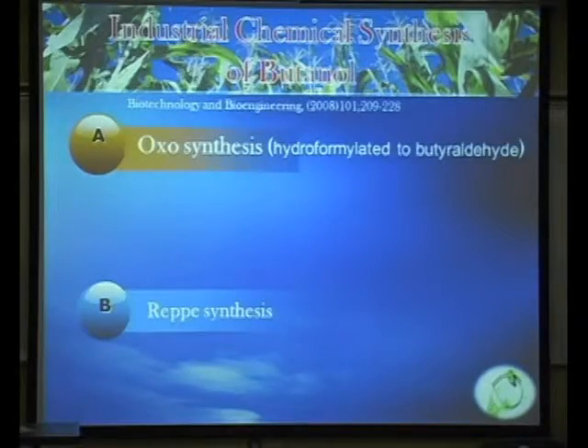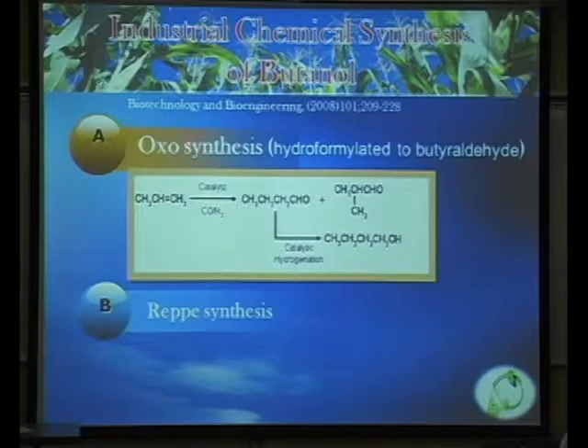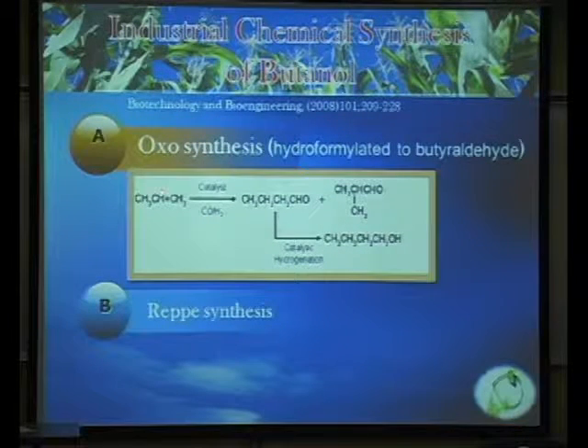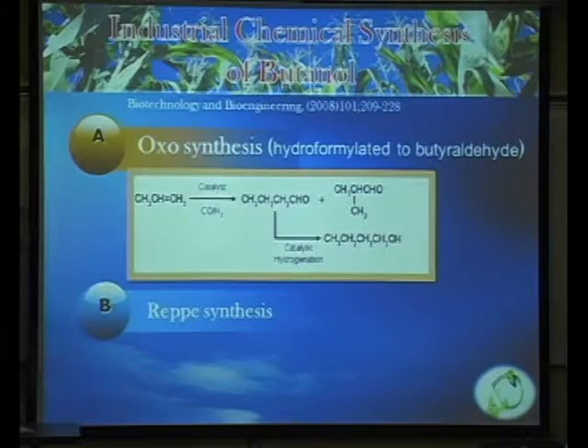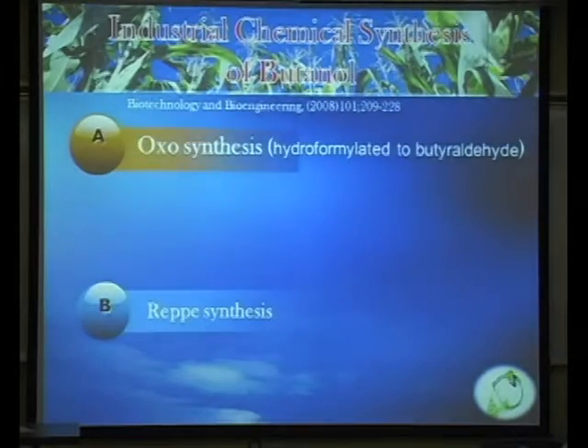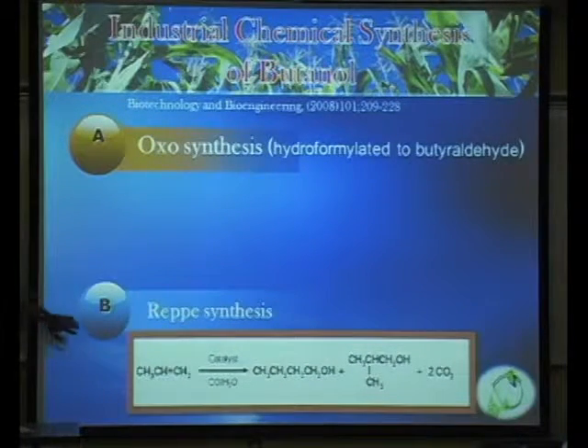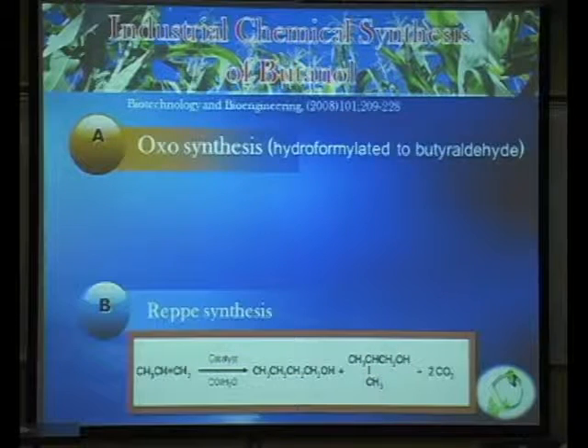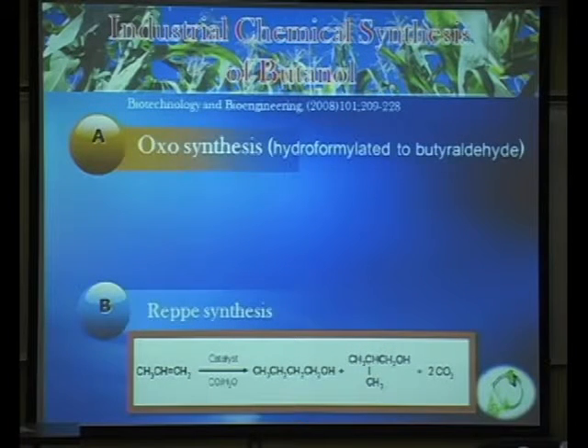Okay, in terms of synthesis in the chemical industry, butanol is synthesized through the oxo synthesis, actually from petroleum-based materials. It starts from propylene gas, and then we can do oxidation and reduction. Finally, using catalysts, we get butanol through an aldehyde intermediate. There is another one-step process, the Reppe synthesis. We can start with propylene gas and different catalysts to produce butanol, both normal butanol and isobutanol. So that's the industrial process to produce butanol.